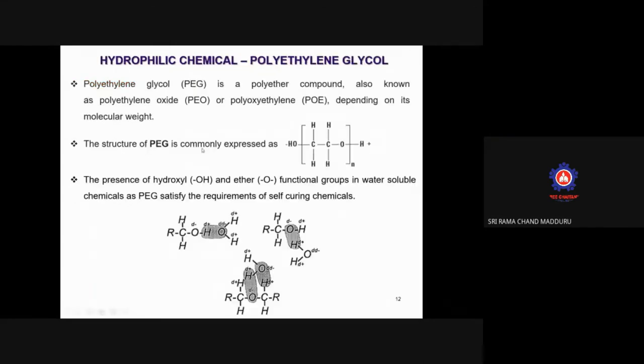Let us see here the hydrophilic chemical polyethylene glycol. It is a polyether compound. You can see the structure of this one. When it comes in contact with water, the presence of hydroxyl and ether functional groups in water-soluble chemicals such as PEG satisfies the requirements of self-curing chemicals. So there is a hydrogen bond that is being formed.